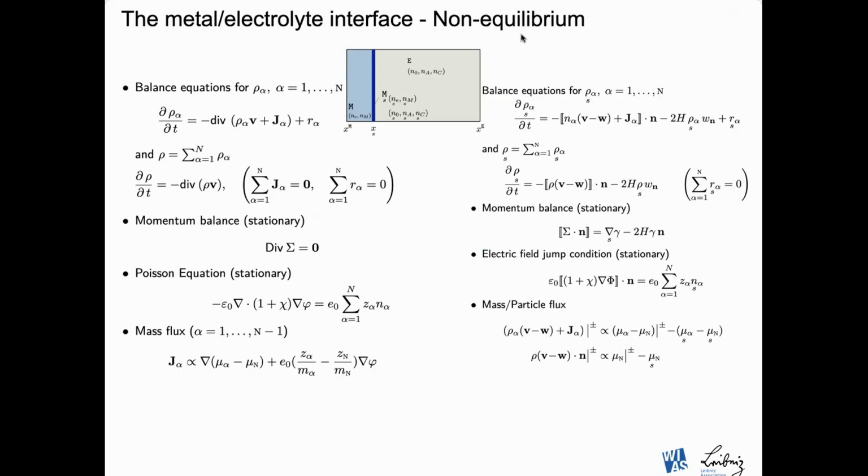So, transitioning now from what we have learned from equilibrium situations in terms of chemical potential functions to non-equilibrium cases. When you step back and ask, and I guess Jürgen also told you about this, the classical Nernst-Planck flux, for instance, you find that ion fluxes are proportional to gradients of chemical potentials, or even combinations of chemical potentials of solvent and of anions.